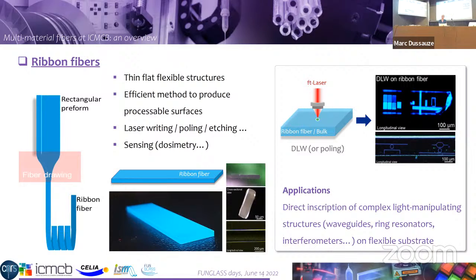For instance, we were able to draw glass slides with a ratio between the width and the thickness of 20, and this ratio of 20 was maintained from the glass slide to the fiber. So we see that with such a ratio, we still talk about fibers, but it's not exactly optical fibers anymore. We use the method for generating a surface, and after we can use this surface for functionalization. Here's an example I mentioned already, the direct inscription of patterns into the systems using femtosecond lasers.